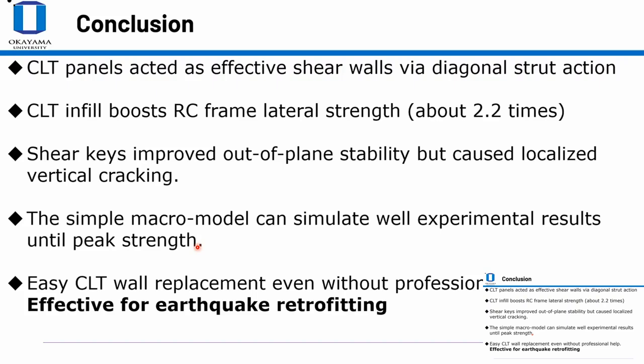So this will be the conclusion of what I have done. CLT panels acted as effective shear walls using diagonal strut action. If you think about RC frames, it boosts the strength about 2.2 times. Without shear keys, it failed out of plane. But with shear keys, out-of-plane stability was better. But actually, we have concentrated stress around the shear keys, which had those vertical cracks. So it's good and not good. The simple macro model, which I represented like a brace model, is easy to use, and it can represent the experimental results until peak strength. After peak strength, there is degradation, which we need to account for. That will be my conclusion.